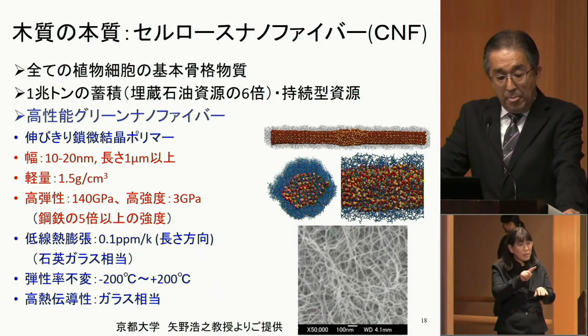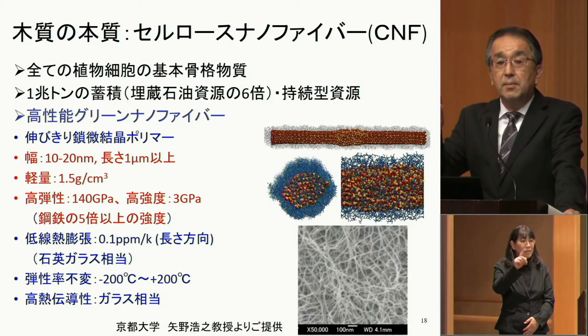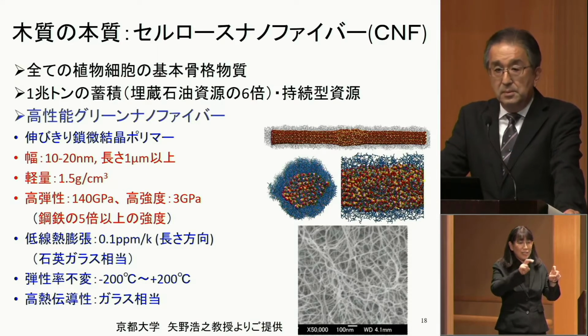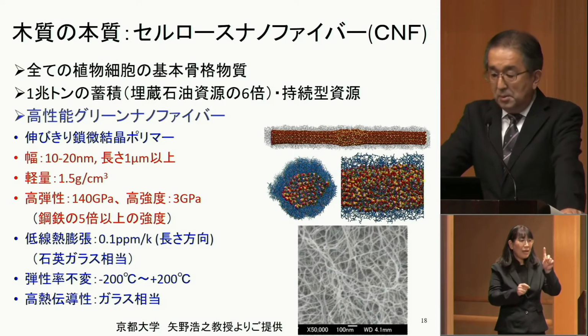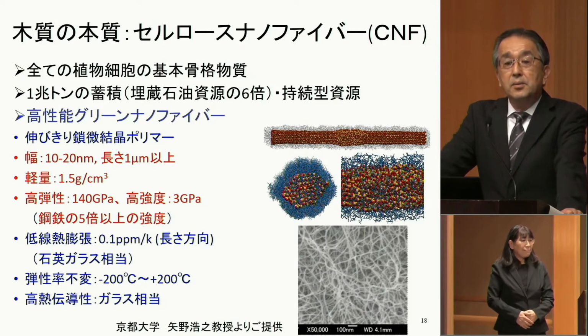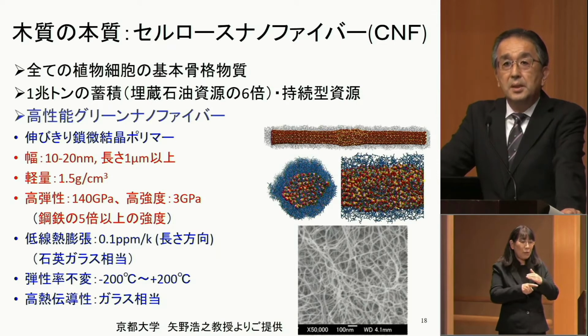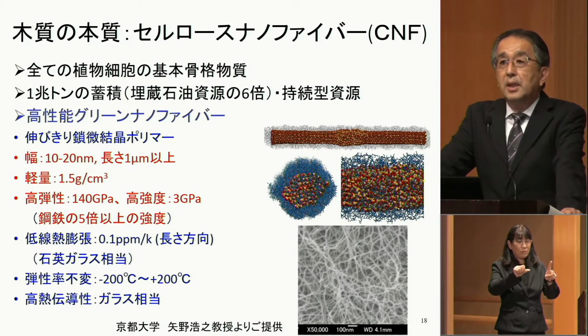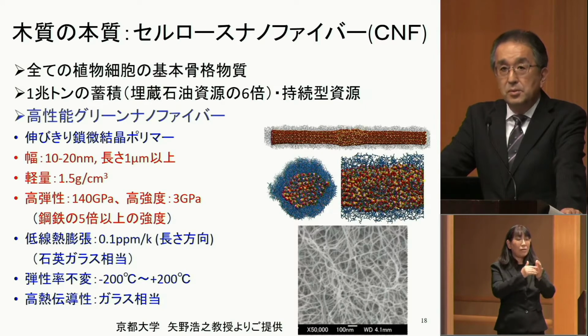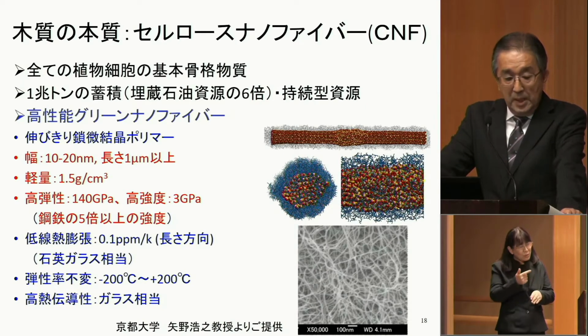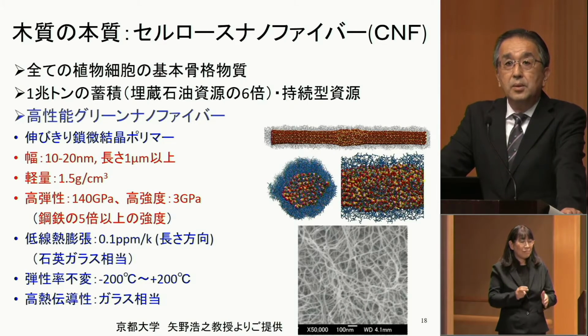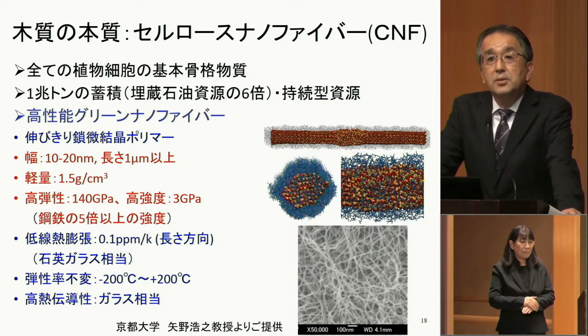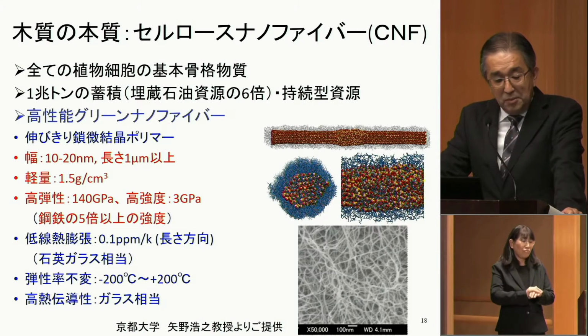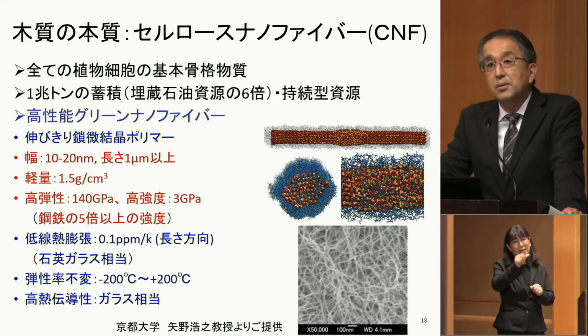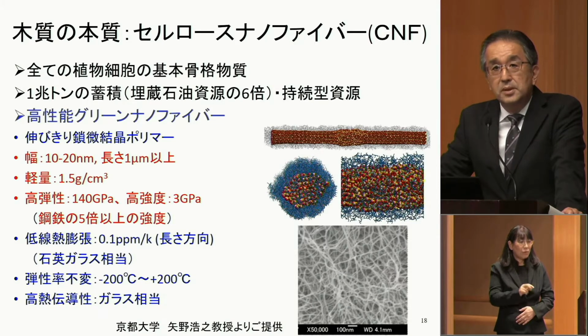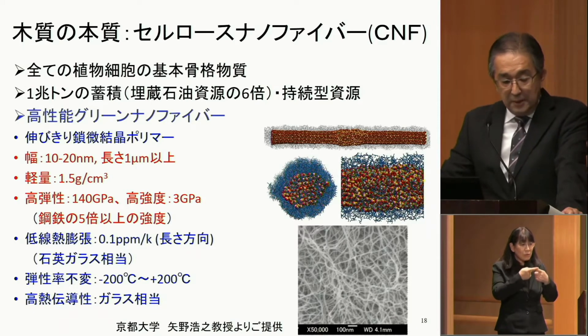Then what are the properties of cellulose nanofiber? The width of the fiber is from 10 to 20 nanometers. The length is more than 1 micrometer, and it's lightweight. That means the specific gravity is 1.5. Iron is around 7 and aluminum 4. So compared to that, it's very lightweight. Also, it's highly elastic and very strong. The modulus is 140 gigapascal. If you look at this figure, it is actually 5 times stronger than iron. So such fiber is incorporated in plastic to reinforce the quality.